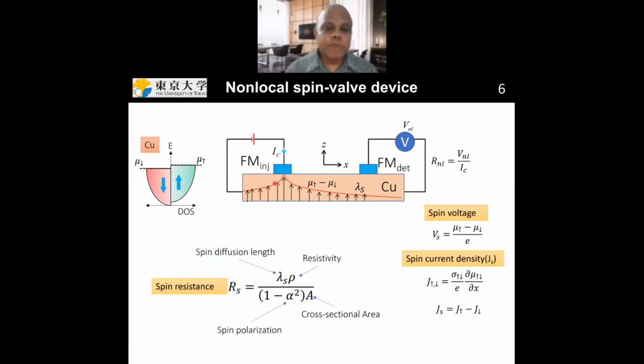Suppose you apply an electric voltage between this ferromagnet and copper. What will happen is that spin polarized currents will be injected into the copper, due to which the electrochemical potential of the copper will be split like in this picture over here. Due to the splitting, we'll have a non-equilibrium spin accumulation just below this injector electrode, and this non-equilibrium spin accumulation will diffuse inside the copper. The diffusion process will create a current, which you can define like this, which is the gradient of the electrochemical potential along this x direction.